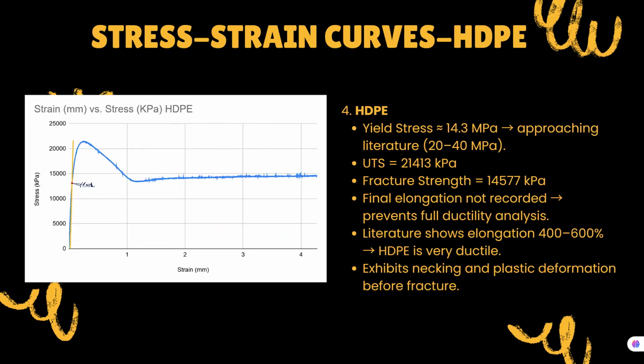And lastly, this is the HDPE. Using the same method, we can get that the yield stress is 14.3 megapascal, approaching the literature, which is 20 to 40 megapascal, and the UTS, the top one here, is 21,413 kilopascal, and for the fracture strength here, the end, is 14,577 kilopascal. And I think this will be the longest elongation in this task.